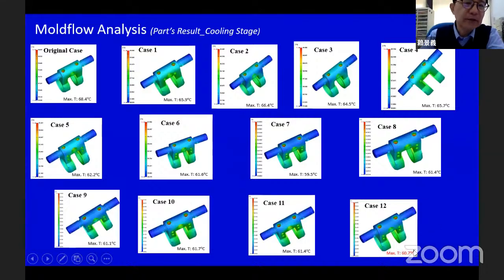So this is not the final result, because the highest temperature actually does not occur on the surface, it is in the central area. We also observe the central area. For the original one, the maximum temperature is 75, and in the final design, we reach 69. So 75 drops to 69. We drop around 6 degrees.